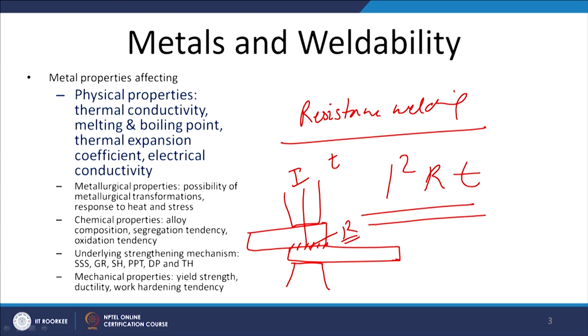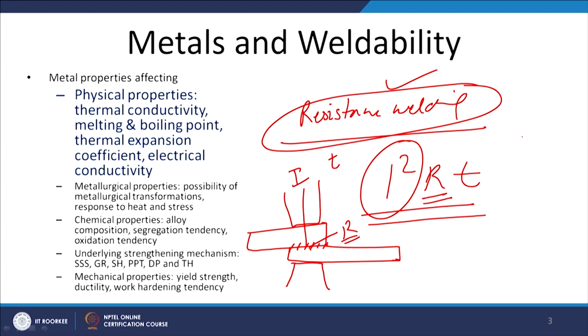So, if the electrical conductivity is high, the contact resistance will be less and it will generate limited heat. So, high electrical conductivity metals will require more current for generating sufficient heat so that the joint can be developed, as compared to metals which have lower electrical conductivity. So, it is always good from the resistance welding point of view that the metal has higher electrical resistance or lower electrical conductivity. For example, the welding of steel through the resistance welding process will be easier as compared to aluminum and copper welding, because both these metals offer higher electrical conductivity and lower electrical resistance. So, we require very high current for generating sufficient heat so that the joint can be developed.